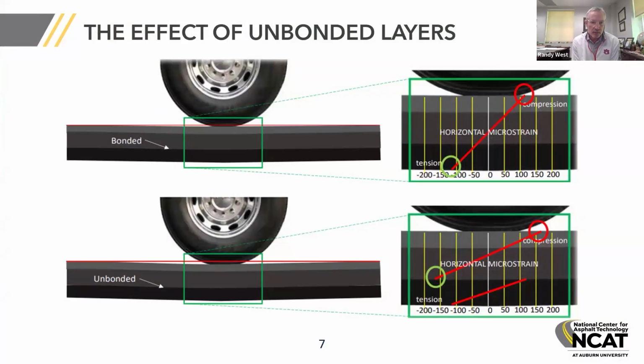This illustration shows a three-layer asphalt pavement, and the top part is where the interface between the base layer and the intermediate layer is fully bonded, and then the right side of that picture shows the mechanistic analysis of the strain level at the bottom of that asphalt. Because as that pavement is loaded, it's going to bend, and we have tension at the bottom, compression at the top. If the layers between the base and the intermediate layer are not bonded, then you actually get a higher strain at that interface than you would for the strain at the bottom in a fully bonded condition. And that higher strain is often what leads to premature failure of the pavement.